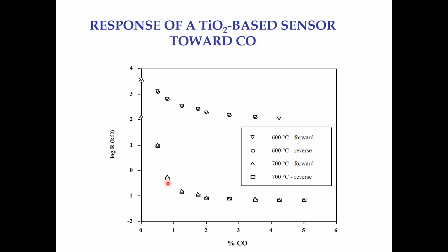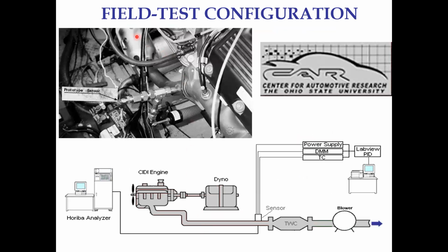And you can see that we're reaching the saturation level as you keep on increasing CO. And the saturation level is achieved when all the surface adsorbed oxygen are consumed by CO. So even if we increase the CO concentration, there is no more surface adsorbed oxygen to react with. So if you want to increase this range of sensing, then one has to use high surface area material like nanoparticles and nanostructures.